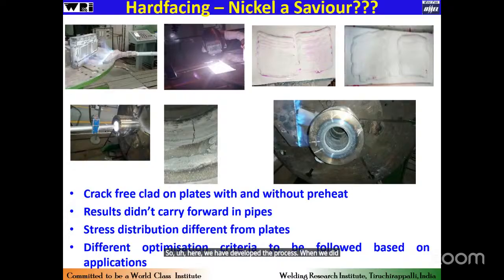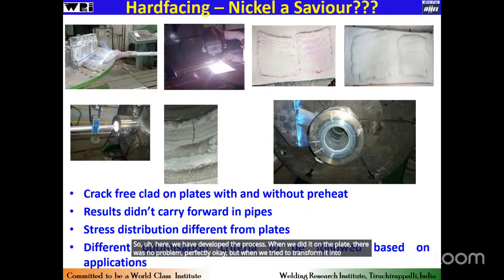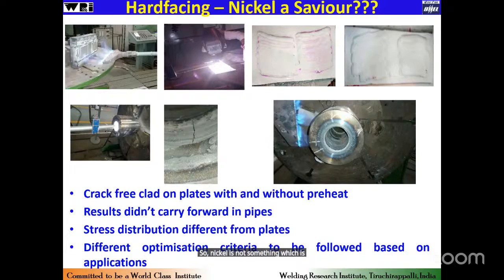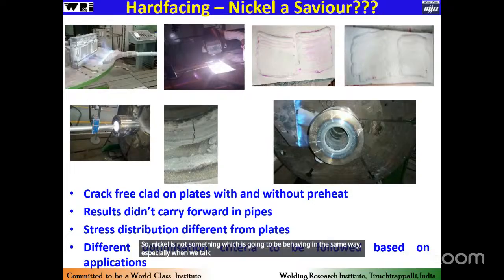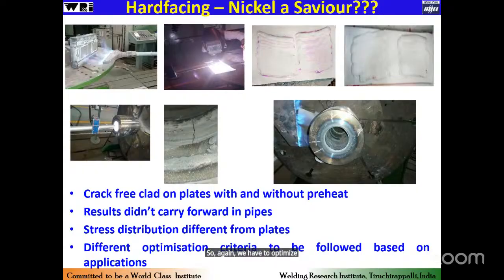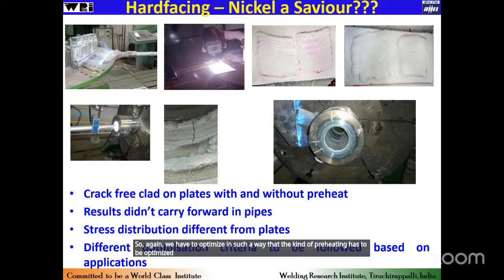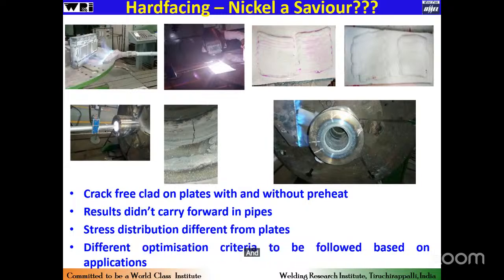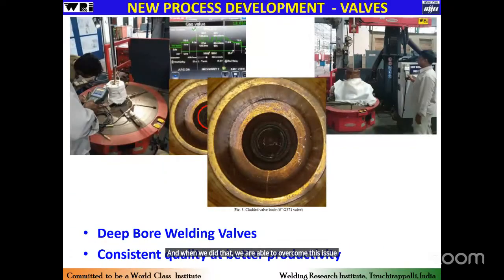When we did it on the plate, there was no problem, perfectly okay. But when we tried to transform it into actual fabrication in the tubular component, and did the deposition inside, we can see that it has actually cracked. So nickel is not going to behave in the same way, especially in such constricted or restricted areas. So again, we have to optimize the preheating and control the cooling rates. And when we did that, we were able to overcome this issue, and this has been optimized.